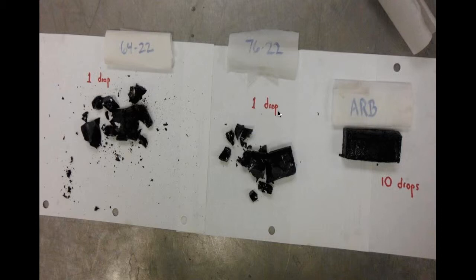That's why we have these slabs, and that's why we purposely put cracks in concrete because it's going to break. Same thing with asphalt, except the forgiveness of asphalt is what's kind of great about it. The cracks that can occur in asphalt can kind of self-heal. But there you can see what will happen in the frigid conditions. This stuff's not going to crack. I mean, it's fascinating.